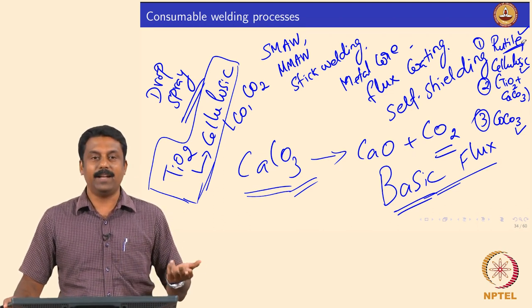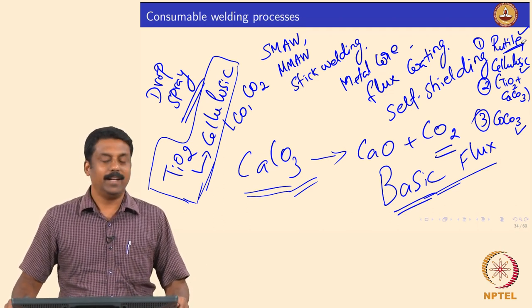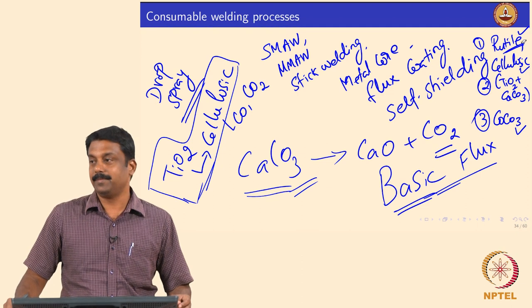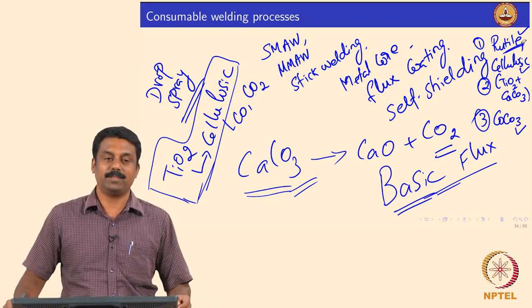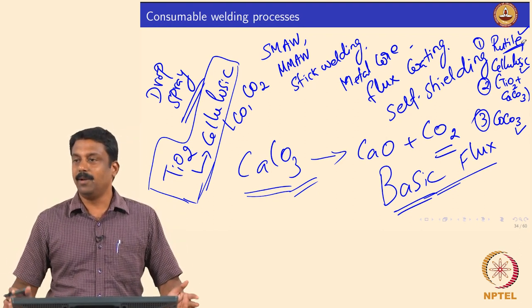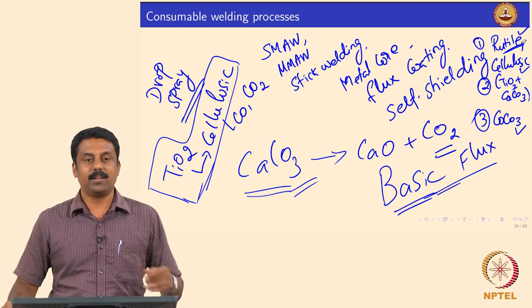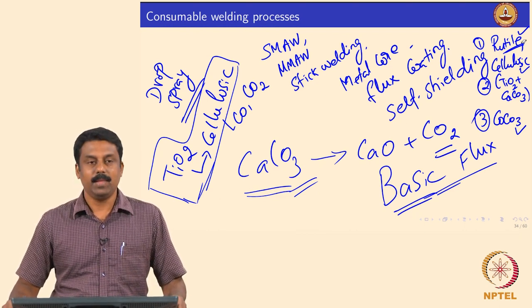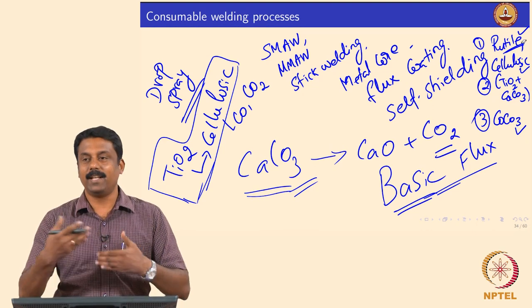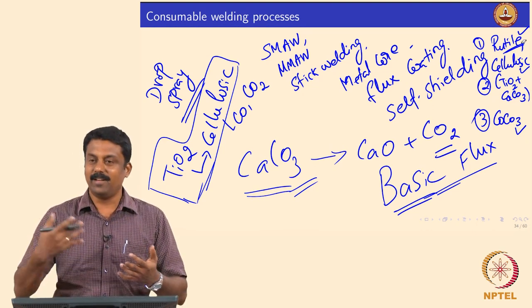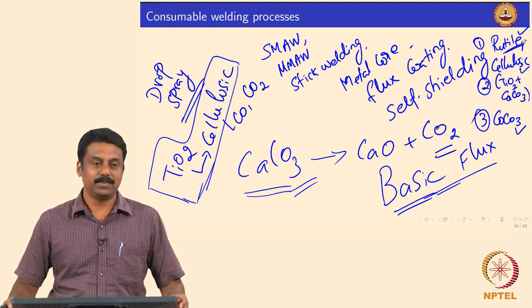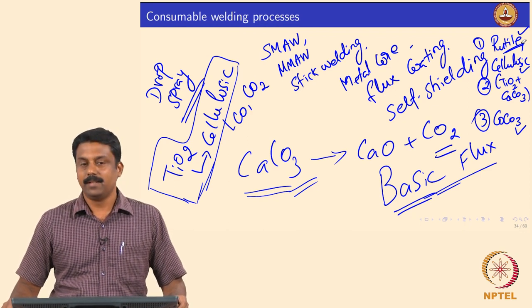In cellulosic material, the majority of shielding gas is generated by burning cellulose, producing carbon monoxide and carbon dioxide — similar to wood burning in a stove, which generates suffocating carbon monoxide. This same reaction takes place when cellulose-base material is burnt in the electrode. Similarly, using a carbon dioxide cylinder produces CO₂ which first dissociates into carbon monoxide and oxygen; the same shielding gas can be generated by burning cellulosic material.